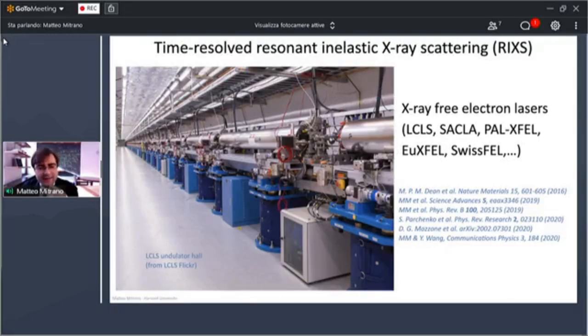This is, as an example, an image of the LCLS free electron laser. The LCLS is a 3-kilometer linear accelerator with an undulator of, I don't remember exactly, but approximately of order 150 meters, that generates very intense X-ray pulses ranging from the soft X-rays to the hard X-rays, with a duration that can go down to a few femtoseconds. And there is work currently to go beyond sub-femtosecond into the attosecond regime.